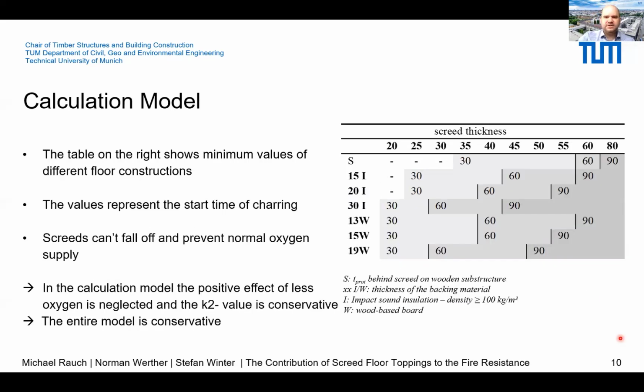For the ease of use, different floor constructions were calculated and are presented in the table on the right. For example, for screed itself, the time reaching 270 degrees of a screed on a wooden substructure is shown in line 1. There you can see that a screed thickness of 35 mm is enough to reach a protection time of 30 minutes. For a protection time of 90 minutes, a screed thickness of 80 mm is necessary. If you have sound insulation under the screed, for example, here you can see that for 90 minutes protection time, a screed thickness of 60 mm is enough, combined with this 15 mm sound insulation.